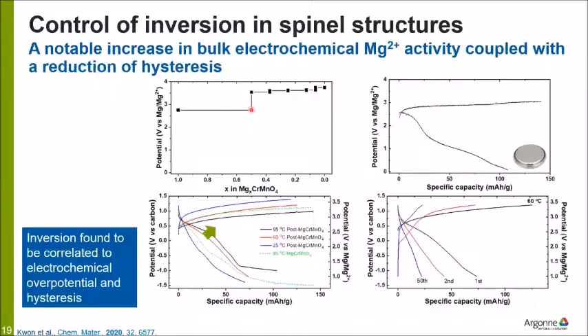Manganese chromium solid solution, and we compare the calculated voltage profile. We look at a couple of different aspects to this. Inversion is found to be correlated to electrochemical overpotential hysteresis. We did different annealing steps to minimize the percentage of inversion, and we can get from as-made 17% down to sub 10% inversion, and we can see that post-annealing versus the as-made, which is the green line. So you can actually see we decrease the hysteresis by moving towards the normal spinel in the structure.